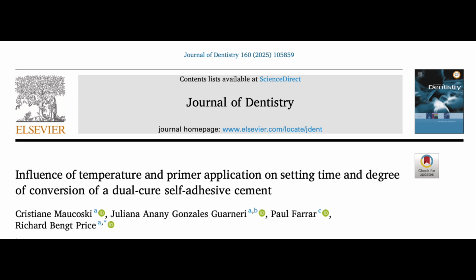But didn't they find something a bit odd with the primer here? Yeah, a little counterintuitive. When they light cured samples with the primer, the initial reaction rate seemed slightly slower than light curing without the primer. Any idea why? Well, the researchers proposed it might be due to how they measured it. The technique looks at a very shallow surface layer, and maybe the primer changes things right at that immediate interface differently than in the bulk material. It's something to consider about testing methods.